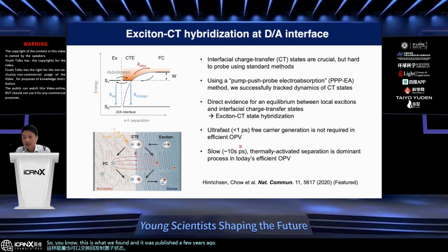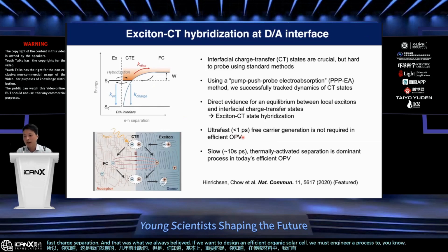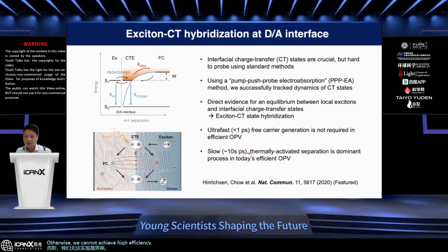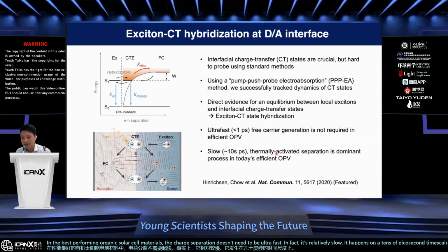The important point is that in the traditional materials we have ultrafast charge separation, and that was what we always believed. If we want to design an efficient organic solar cell, we must engineer a process to rapidly pull the electron away from the hole. Otherwise, we cannot achieve high efficiency. But what we have now found is quite the opposite. In the best performing organic solar cell materials, the charge separation doesn't need to be ultrafast. In fact, it's relatively slow. It happens on a tens of picosecond timescale, and it's very much a thermally activated process.